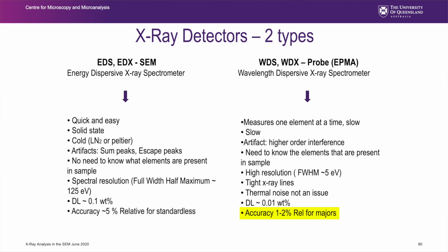Accuracy, 1 to 2% relative for majors. I can control that by running reference standards as calibration checks. But every time you find it's not good enough, you might spend hours fixing it up. It's not a quick day on the probe. In fact, some of my best analyses on the probes have been 3-day experimental runs. So that's the probe and that's the SEM and how I use them differently.